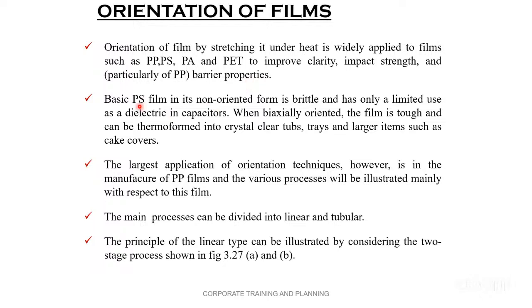Basically, polystyrene film in its non-oriented form is brittle and has only limited use as a dielectric in capacitors. When biaxially oriented, the film is tough and can be thermoformed into crystal clear tubs, trays, and larger items such as cake covers. See, these are the benefits of biaxially oriented film versus non-oriented film.